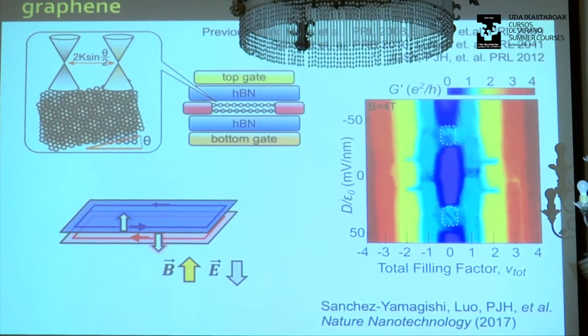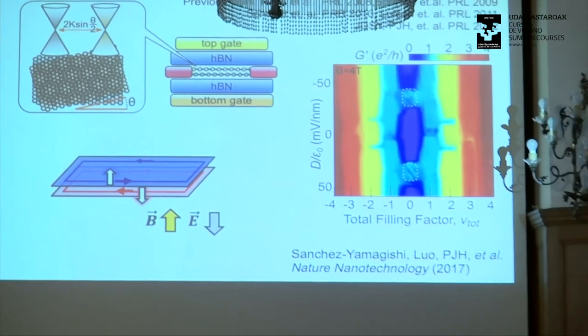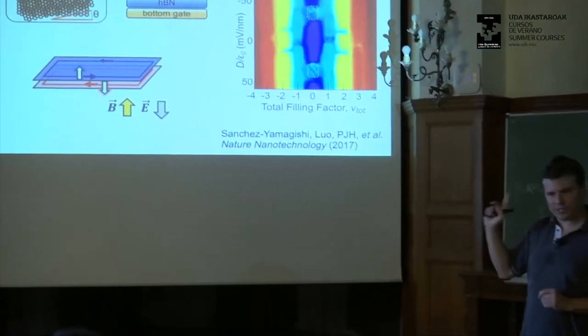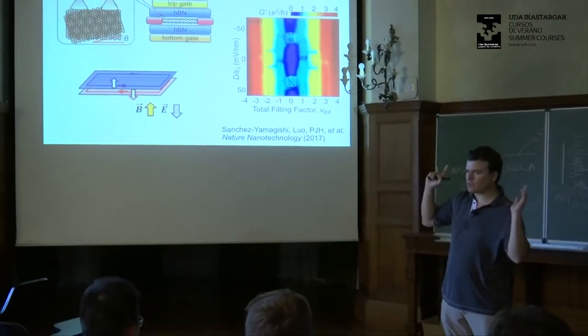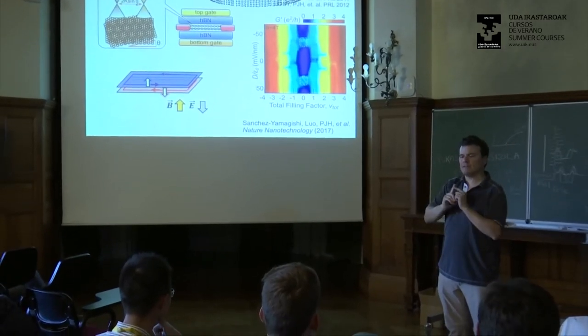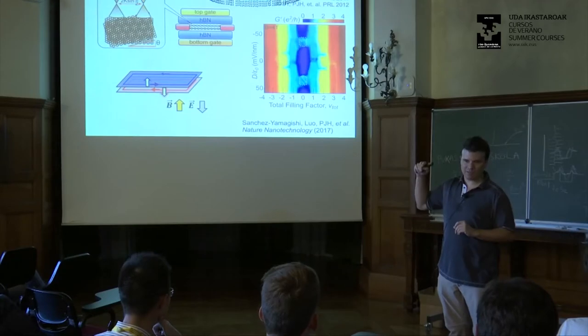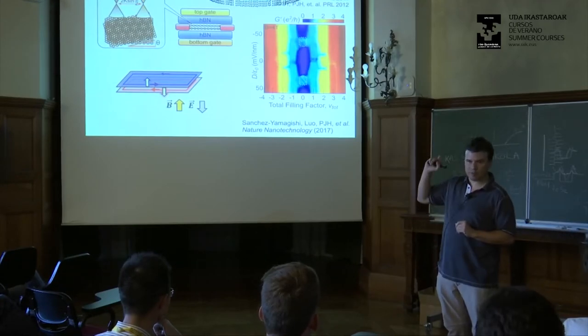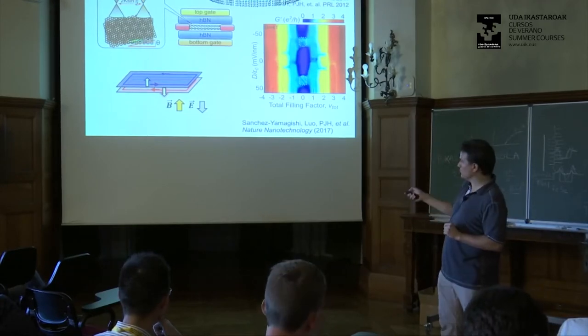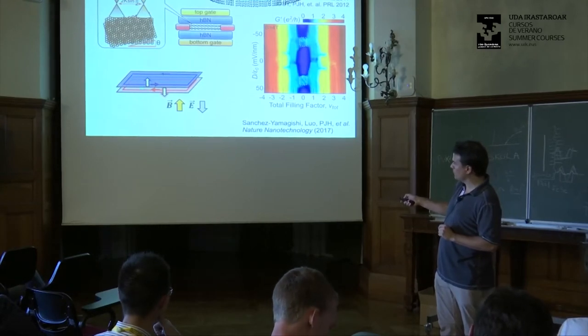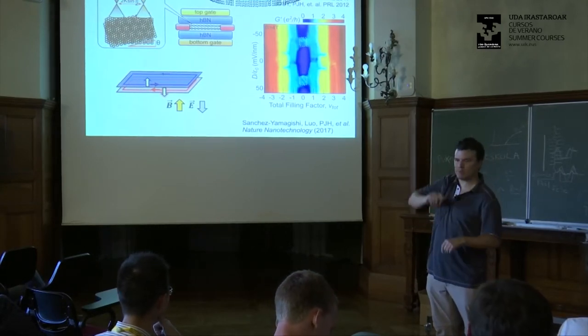There have been many previous studies that have shown that if you take monolayer graphene and apply a field of order a few Tesla, you have broken symmetry states, purely spin polarized at filling factor 1 and minus 1, with opposite spin polarization for 1 and minus 1. And that's what we're doing. We're putting filling factor 1 here, minus 1 here. So we have opposite spin polarizations.